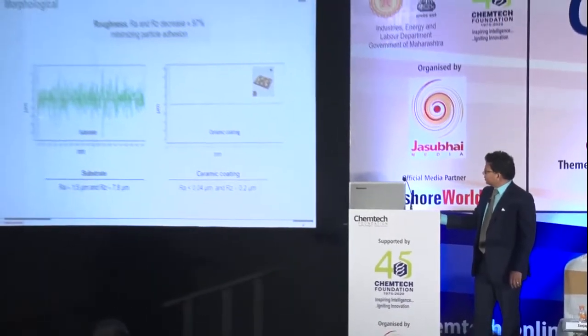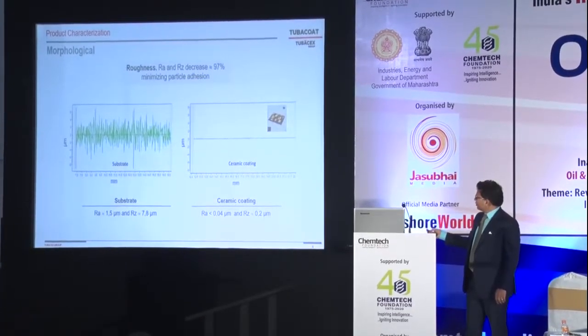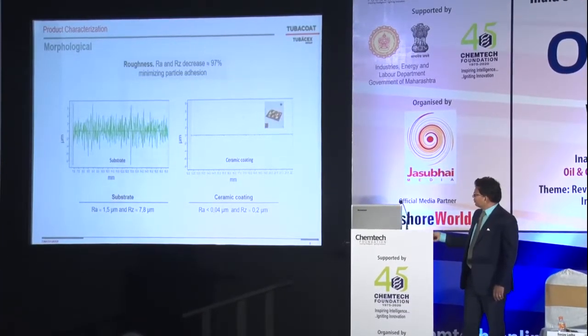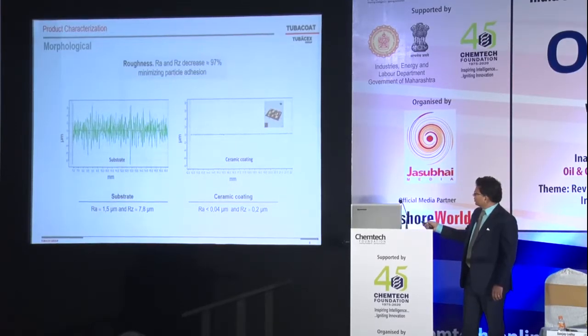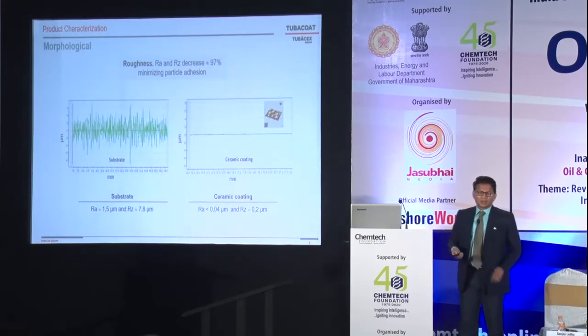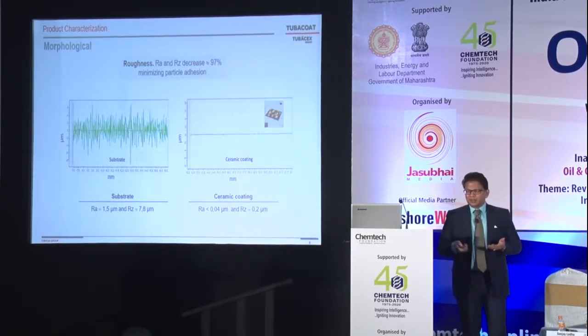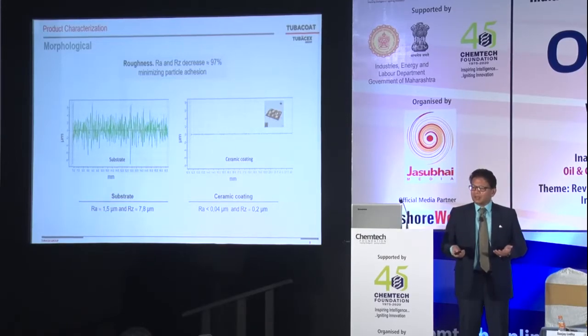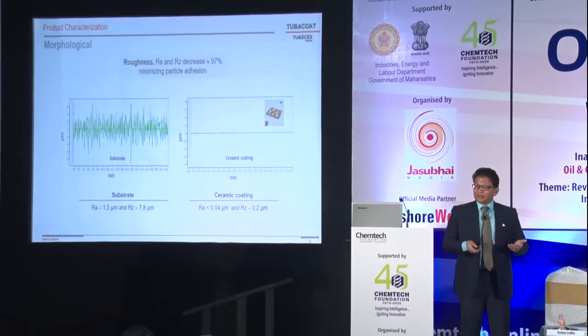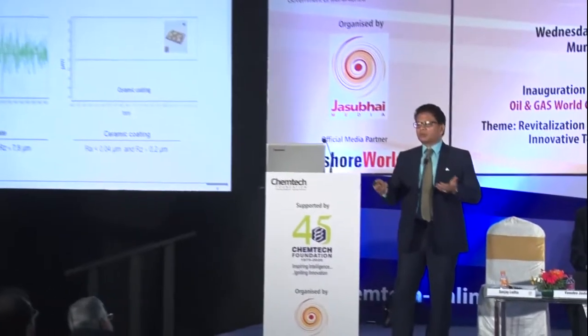So one of the key properties you can see, if you look at this slide, is any substrate, austenitic steel, that's not coated, and this is a ceramic coated same substrate. And what you see is by coating with the Tubacoat technology, you reduce the roughness by 97%. We know the basic logic: the smoother the surface, the less the chance and tendency for fouling. The rougher the surface, you have metals and contaminants in the feed, they come and deposit, and that further extends the fouling. And so we eliminate this property by giving you a surface that's more like a mirror.